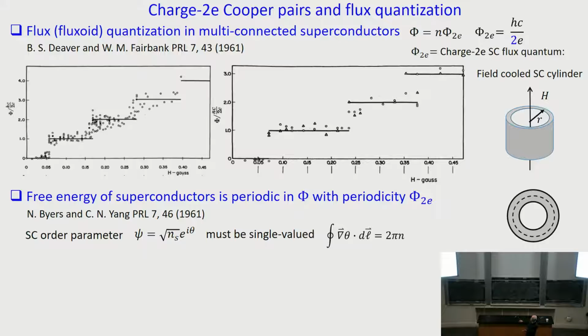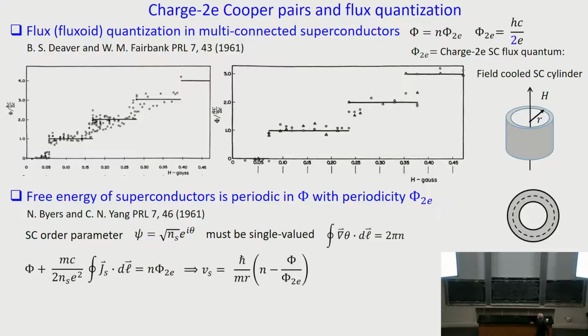This order parameter has to be single-valued, therefore this kind of quantization must exist. And you can write this as the flux plus the flux screened by the supercurrent. This is called the fluxoid. It's quantized in units of this. And that leads to a velocity oscillation in units of 2e flux quantum.